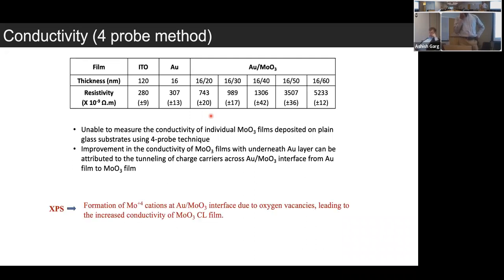One thing that we found is why it leads to higher conductivity, and we did some XPS. What we find is that moly oxide has a moly valence of +6, and it goes to a +4 state, and this +4 state leads to formation of oxygen vacancies, and these oxygen vacancies lead to higher conductivity of the moly oxide capping layer film, which improves the charge collection.